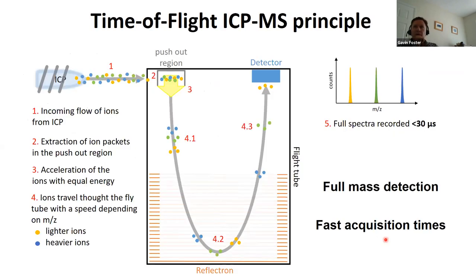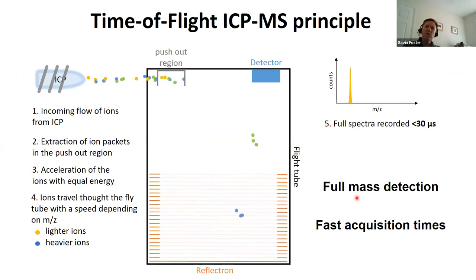We've heard a lot about time of flight ICP-MS already, so I won't labor this. But briefly, the advantages of time of flight ICP-MS is that you get full mass detection and very fast acquisition times. It's a really nice video that the guys at Nu have provided. The main points here are that you have ions generated in the ICP. They make it to the push out region, and then the extraction pushes ions into the flight tube with the same energy. And then those ions travel through the flight tube at different speeds, depending on their mass to charge ratio. That then allows you to separate out the ions.